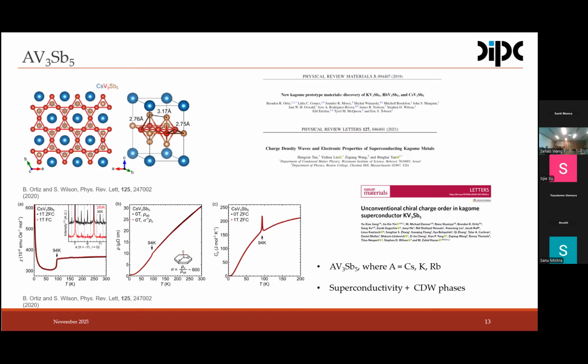In any case, what we know so far, and it is for sure quite stable and quite solid, is that the charge order is driven by the primary order parameter in this compound, which is actually the L point and not the M. There are reports now that the charge density wave is driven by the condensation of a soft mode, which was experimentally observed. Papers are on arXiv. And also this compound shows superconductivity. There is also no solid establishment about the origin of the superconducting order. The possibility of chiral charge density waves is also highly discussed, and so on and so forth. In any case, I'm not talking about this one. This was the first compound which brought this hot topic to where we are right now.